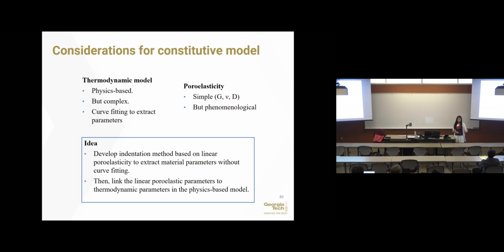And after determining what method to use, we also need to quantify the behavior of the material. In the literature, there are two general ways to model the material. One is the thermodynamic model, as I just presented. This is good because it's a physics-based model. The material parameters are directly related to molecular features of the material, so it has a physical meaning, but the theory is very complex. At the end of the day, it's very difficult to get an analytical solution, and you still have to do curve fitting to get material properties. But in the literature, there is also another theory called poroelasticity. This is a well-established theory, and you have a lot of existing Green's functions that you can take advantage of to get the analytical or semi-analytical solution of the problem.